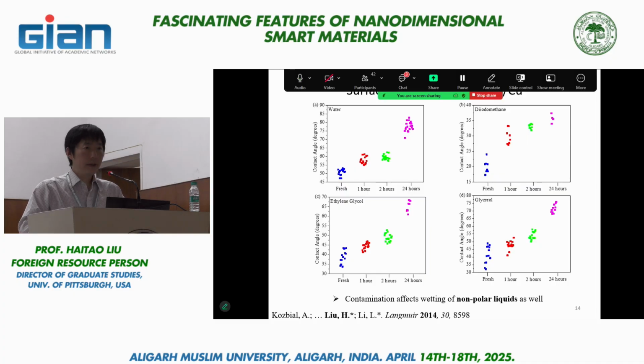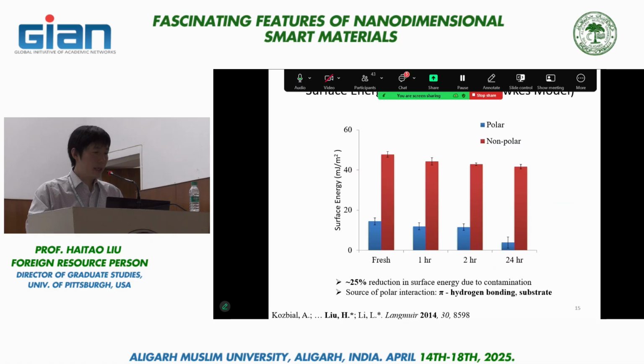If we feed the data into this model, we come to the surface energy diagram shown in the middle. What you see here is that after 24 hours, this is the so-called third-day graphene, but it is also the graphene, or graphite, most likely measured by people in the previous literature. The non-polar component is dominating, and the polar component is almost zero. Now, a materials chemist looks at this and says, oh, this makes sense. Obviously, graphite and graphene are non-polar, so there shouldn't be any polar interaction. And if you look at the data measured after 24 hours of exposure, it sort of validates your model.